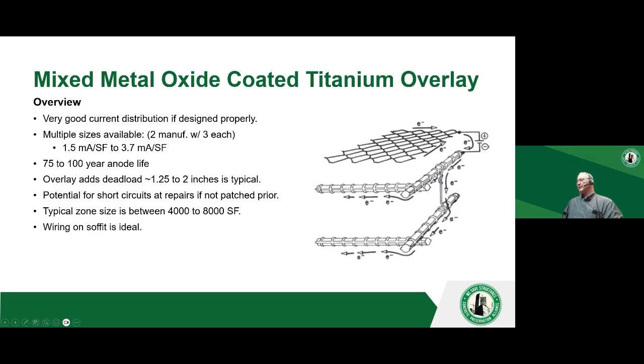Most of the current is delivered to the top reinforcing steel. That's where you get the chloride contamination. That's where you need it most. But it will also provide some current to the bottom reinforcing, and it'll polarize both layers depending on the thickness of the slab. And there's multiple sizes of mesh, and they have 75 to 100-year anode life.